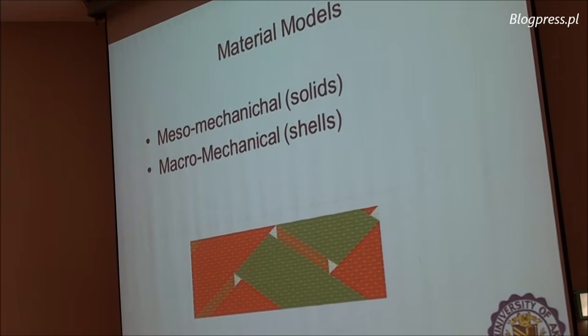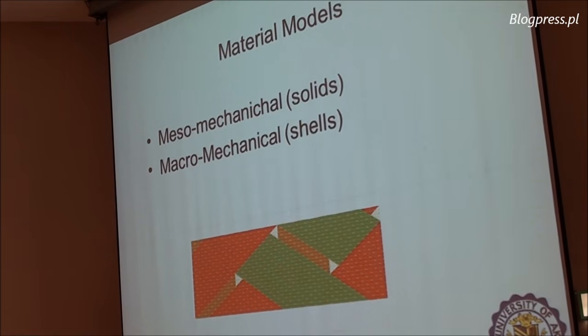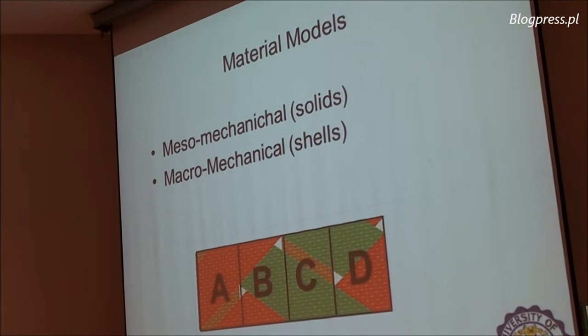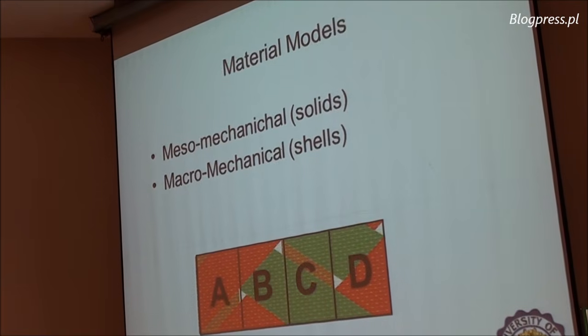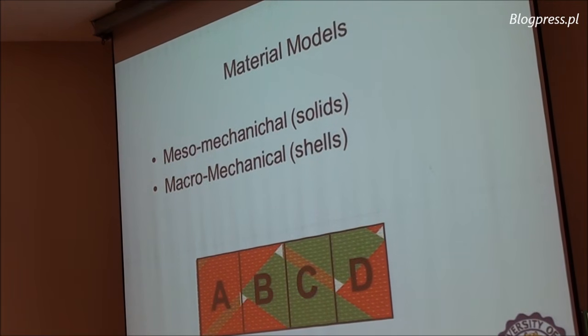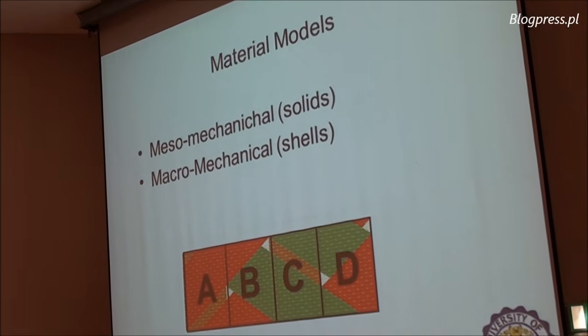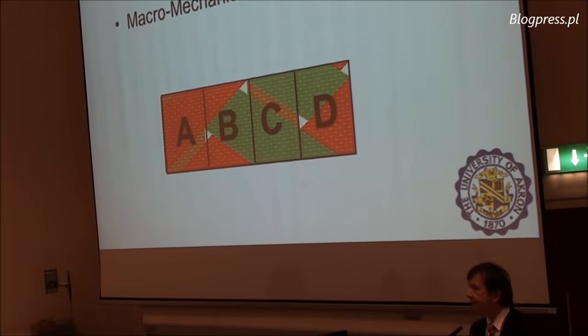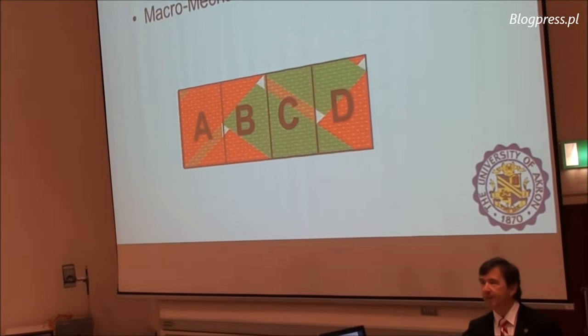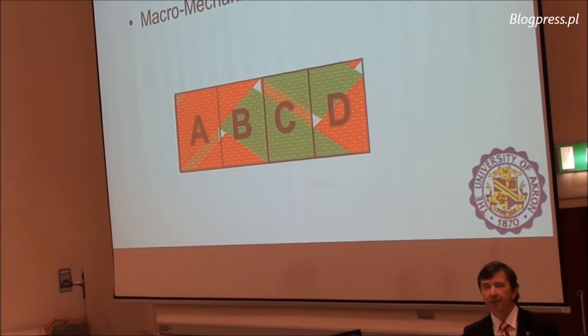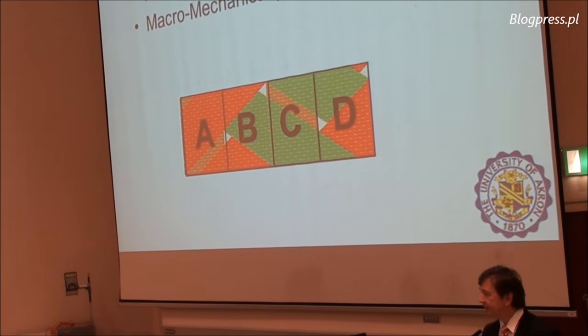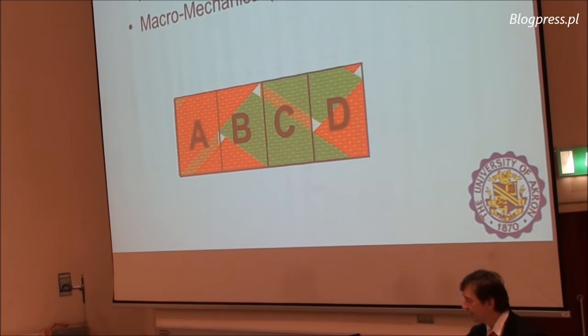And then all these tests are put together in the mesomechanical model, which is shown here, and macromechanical model. For the macromechanical model, we divided the braid, the so-called representative volume element, into subsections A, B, C, D. In subcells A and C, there are fibers in plus, minus, and 0 degrees orientation, and B and D are plus, minus 60 degrees orientation.